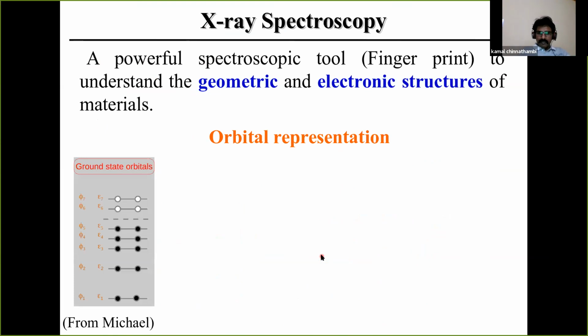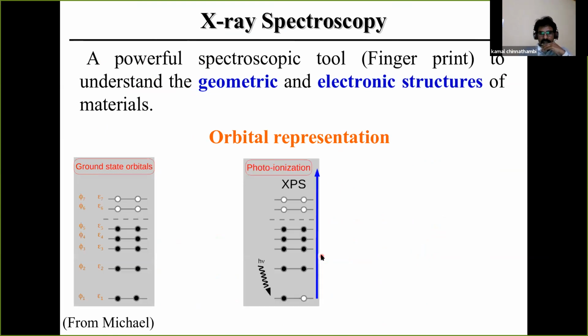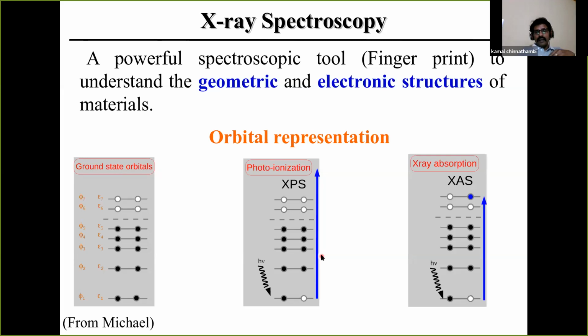In the previous presentation it was also mentioned that in the ground state all the levels below the Fermi level are completely filled, and above it they are empty. But when you apply X-rays, either we have XPS, where the core electrons are ejected out of the system, or the core electrons are transferred from the core to the unoccupied states. In both cases, we have a core hole present in the system.